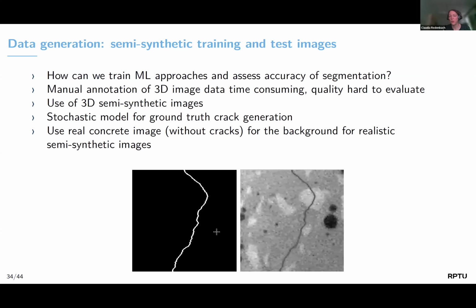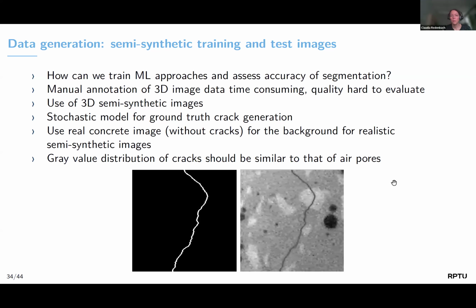And then we had a perfectly annotated pair of a gray value image looking like a CT scan of concrete with a crack, and the mask for the ground truth annotation. Regarding the gray value distributions, here we made use of the fact that we could look at the pores. So the gray value distribution in the pores was used to decide on the gray value distribution in the crack.